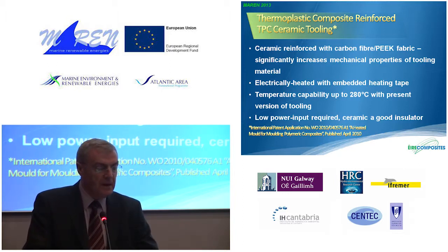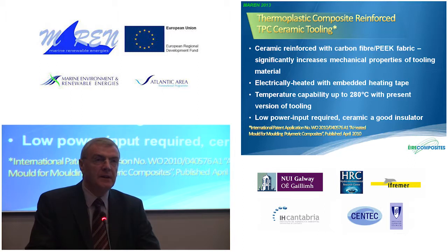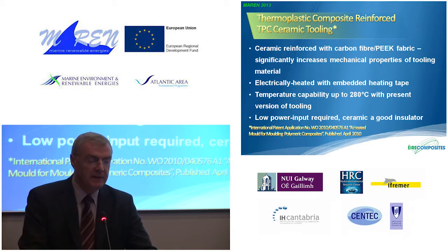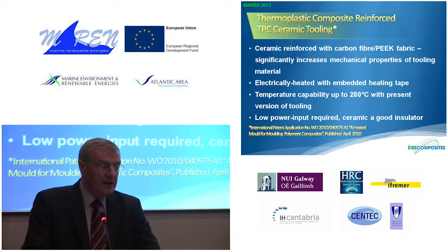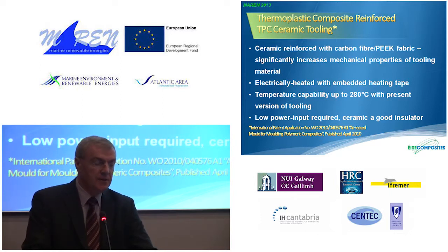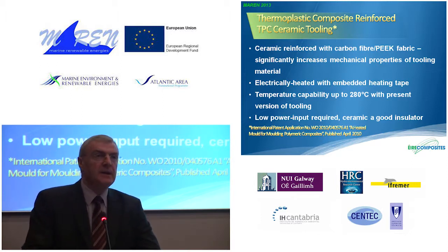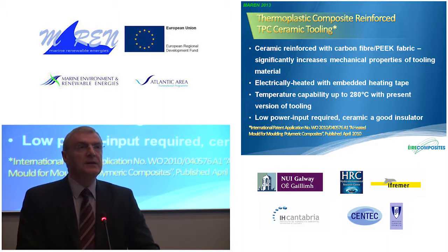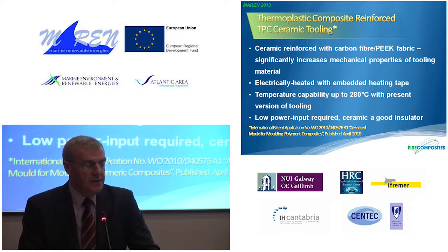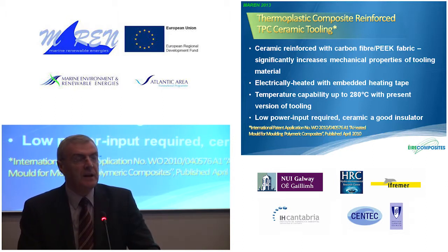composite products. We also, instead of applying heating on the back or B side of the mould, embedded the heating system while manufacturing the mould. And this resulted in a very efficient heating system, which had the capability of up to 280 degrees without any degradation of the mould during cycling up to several thousand cycles. And because the ceramic is also a good insulator, it had the advantage of retaining the heat, and you had very little heat loss during the process, which made it a very efficient system as well.